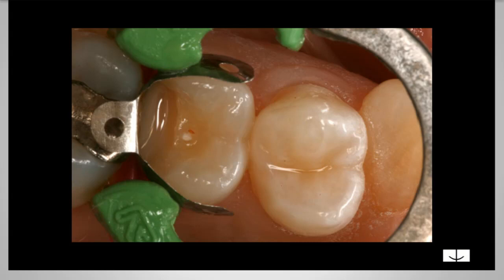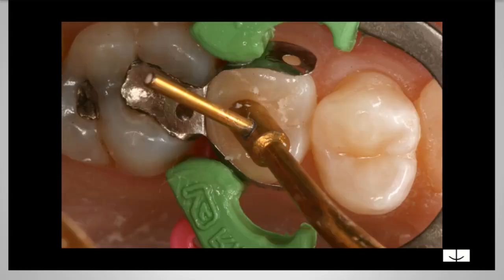Next I go in, this is with GC's Kalore composite resin. I like to use this instrument. This one's by Garrison, and it allows me to put in some nice anatomy before I cure it. And I think that putting that in can really decrease the amount of time you're spending contouring the composite after you're done. And so packing that in there, I like to do 1 increment of flowable and 1 increment of the packable resin. If I can decrease time, increase predictability, that's what I'm all about.